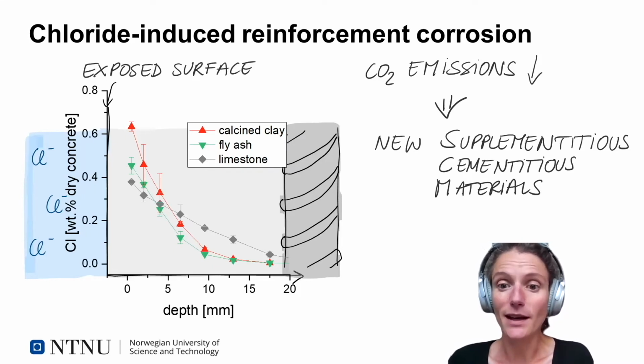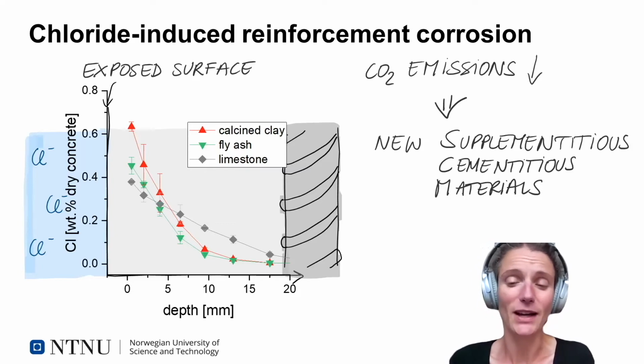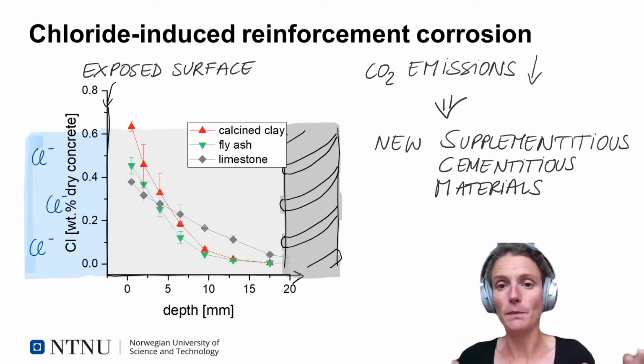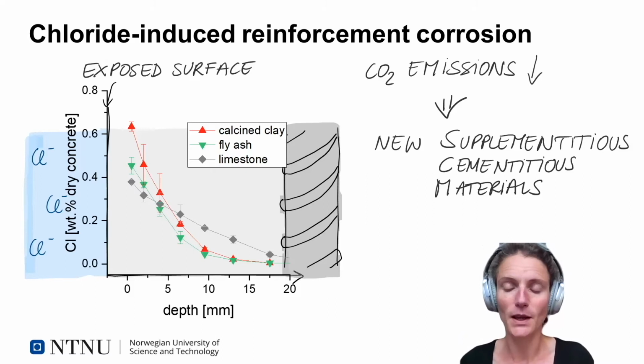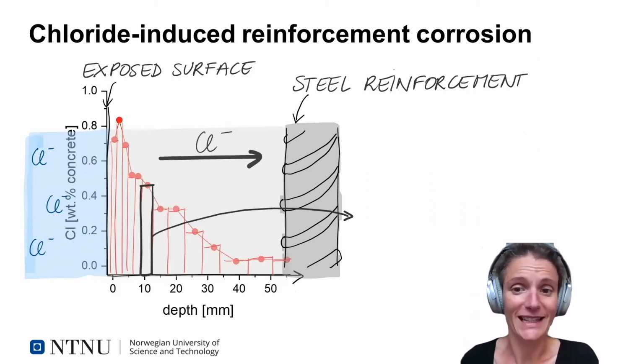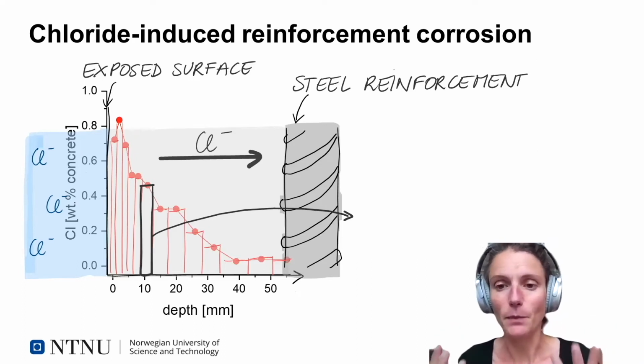So the challenge is that we're running out of the conventional SCMs, such as fly ash and slag. So we urgently need to start using new SCMs, which have a different composition, different reactivity, so they will affect the chloride ingress resistance of the concrete. And then we don't really have the time to obtain long-term field data for these empirical models. We actually really should start to use mechanistic models that can cope with the variability of SCMs we're going to have on the market soon. So for these mechanistic models, that's where chloride binding is a very important aspect.